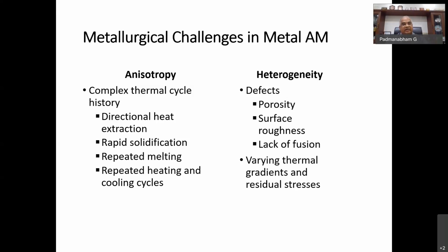In laser processing, the melt pool size is so small that the material goes through rapid cooling, almost 10,000 Kelvin per second, leading to very fine microstructures and very small heat affected zones. And another thing that happens is repeated melting, because we are doing layer by layer. You put a layer and then you put the second layer. When you do the second layer, some amount of remelting takes place.